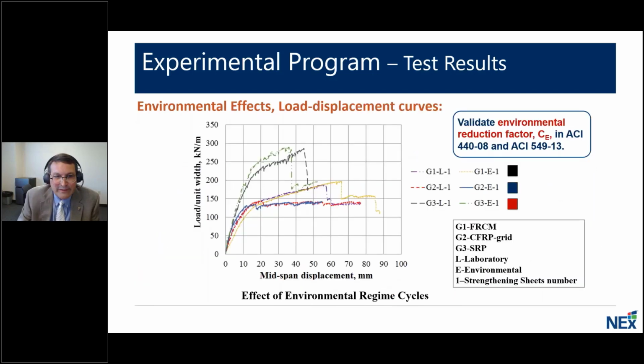which was a good finding as well. When we look at now one-ply systems with just the load displacement curve here in terms of reduction of capacity, the color coding shows all one-plies in the environmental chamber. Again, we see little effect for the SRP and the CFRP systems, with an actual improvement in the FRCM system due to that post-cure effect. So that's one advantage we observed of the 3 different systems here. And again, the reason we were looking at this was to see what might be an appropriate C sub E factor for 440 or 549 for the use of these materials.